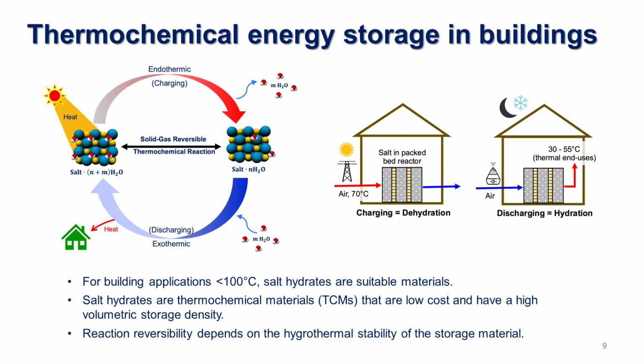So what does this reaction look like? So essentially you start with your salt hydrate. You apply heat and that results in the endothermic reactions. You're providing energy, and you can think of that as charging our thermal battery, and that ends up dehydrating the salt. So your water molecules leave, and you're left with the salt at a lower hydrated state. We can now run the reverse reaction when we want the energy. We will supply water molecules in the form of relative humidity or moisture, and the salt will take in that moisture, and that is an exothermic reaction. That's going to now release heat, which we will use for our building application. So this you can think of as the discharging of our thermal battery.